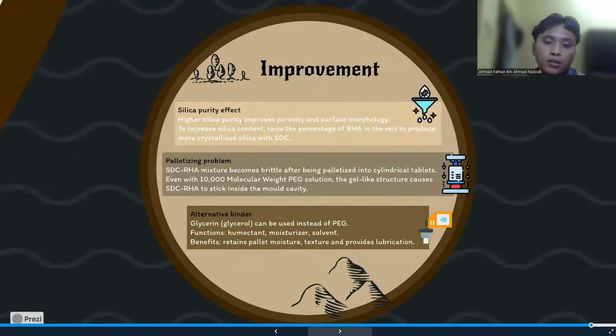For further recommendation, higher silica purity improves porosity and surface morphology. To increase silica content, raise the percentage of RHA to produce more crystallized silica with SDC. For the pelletizing problem, an SDC RHA mixture becomes brittle after being pelletized into cylindrical tablets. With PEG solution, the gel-like structure causes SDC RHA to stick inside the mold cavity.